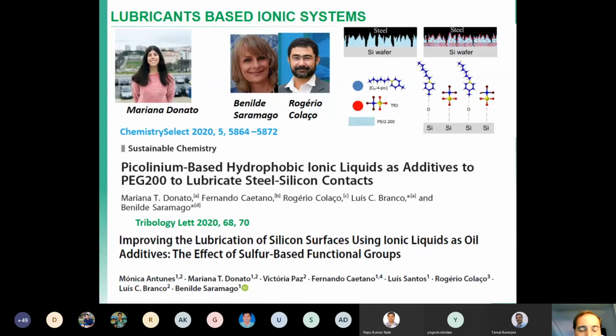And here it's important to consider sulfur anions. This is an observation of particular interest. If we are using a sulfur anion like triflate, trifluoromethanesulfonate, we can improve this kind of application. Why? Because the sulfur anion can interact with the silicon surface, and in particular it's possible to consider it like a film, and this is very important for the lubrication process.